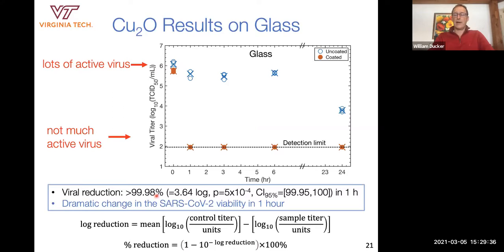99.98% in 1 hour. Now, biologists like to talk in logs, which is equivalent to what we as chemical engineers might call orders of magnitude. So there's 3.5 orders of magnitude here because this is a log scale. So a biologist would call that 3.64 log units of reduction. So that's the formula for how you calculate log reduction. However you count it, it's a really dramatic change in viability of SARS-CoV-2. So of course, we were super happy about this result.